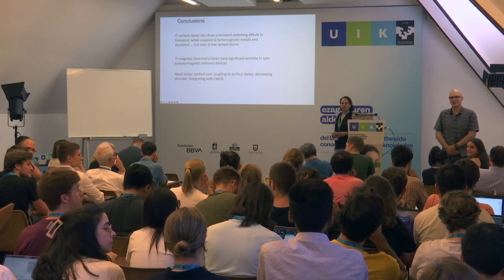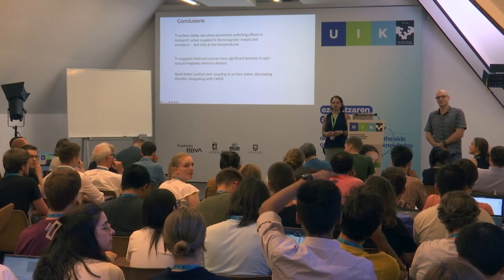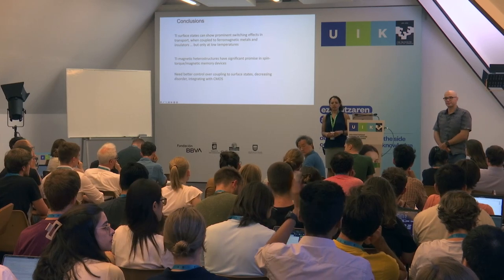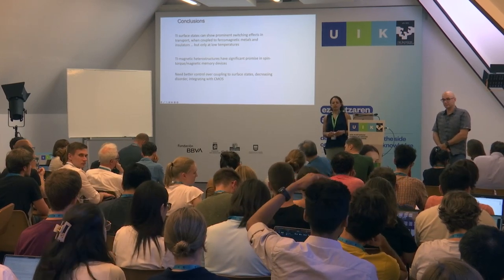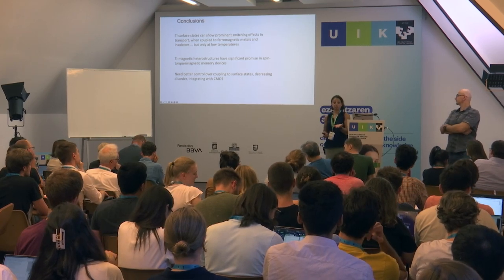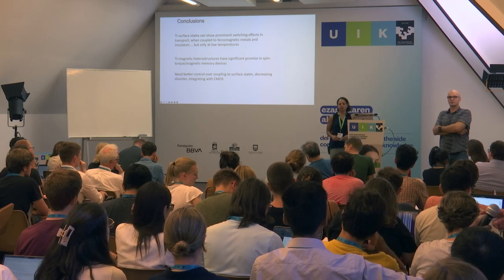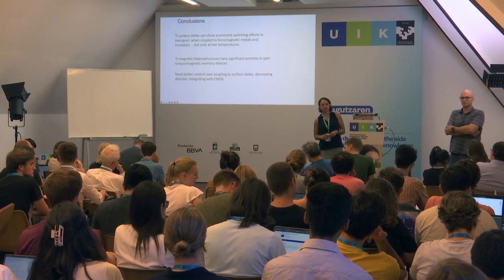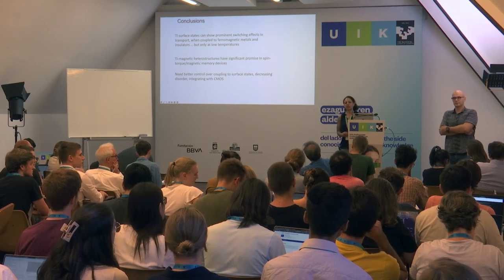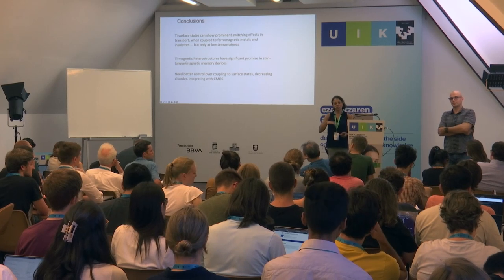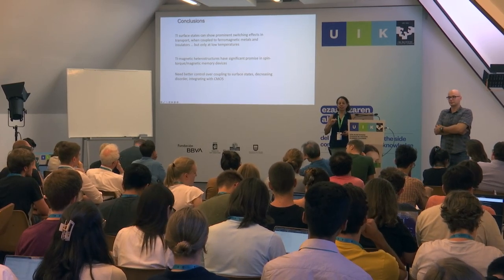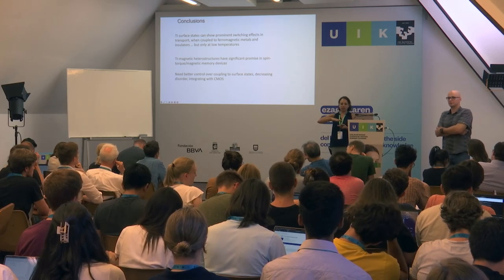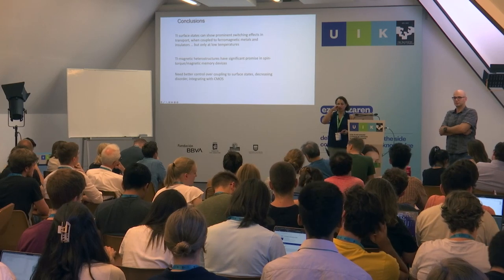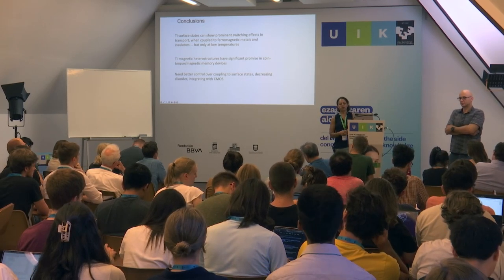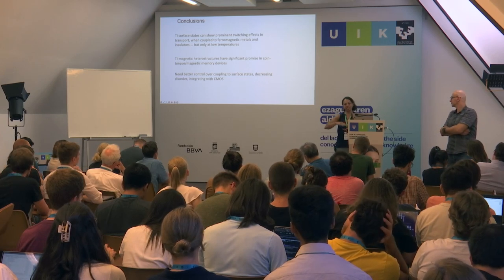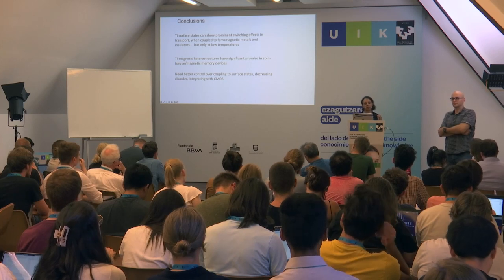Is there any work going on synthesizing some naturally occurring heterostructures of these types of materials, like transition metal dichalcogenides? Could we take the 2D layered materials and make stacks of these? Yes, you can, and I think that's a really interesting direction, and you could see a lot of these behaviors. The only issue there is you want to really control the magnetization and make sure it's very robust. We did choose cobalt platinum because it has a known out-of-plane moment. A lot of these other materials may or may not have the magnetization that you want for these experiments, because the bismuth selenide has an out-of-plane moment, we think. But yes, I think probably the best direction to move forward is by layering these with magnetic 2D materials.